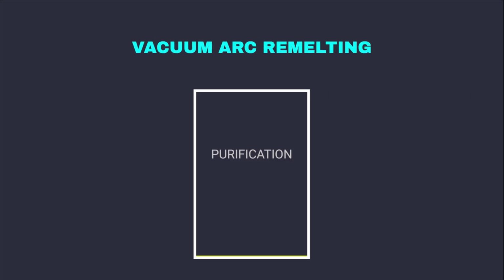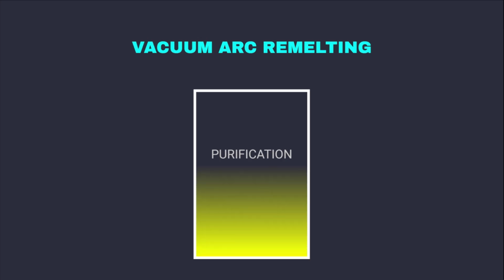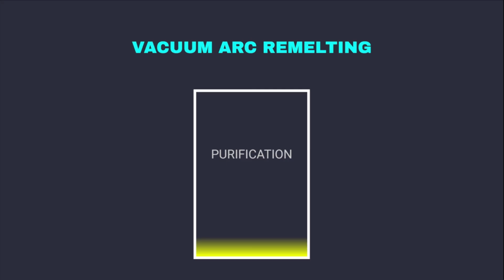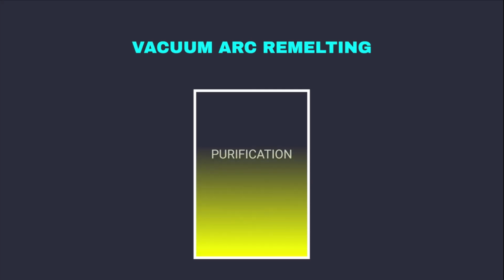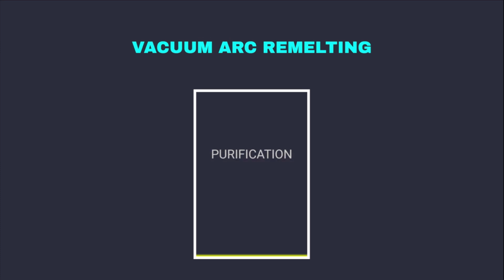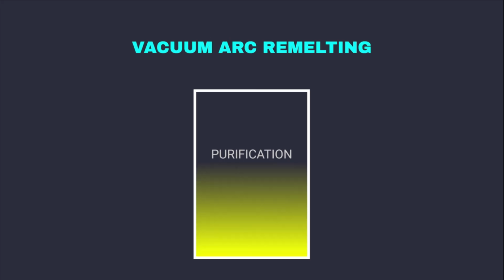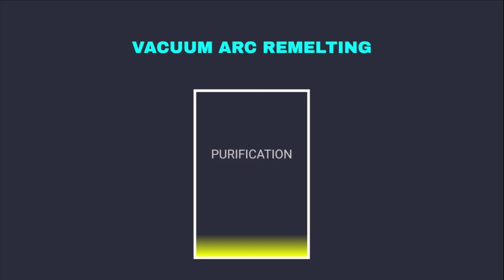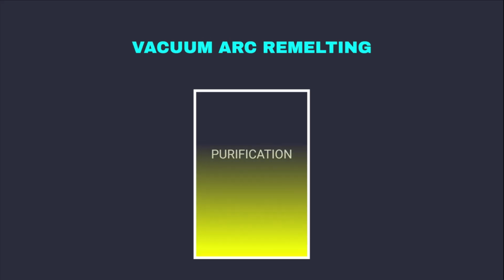Raw titanium sponge, the porous product of the Kroll reduction process, is unusable for aerospace applications until it is consolidated and purified. The acquired sponge had to undergo multiple stages of vacuum arc remelting. This process involves pressing the sponge into electrodes and melting them under high vacuum conditions, often 2 or 3 times, to remove volatile impurities like magnesium chloride and ensure chemical homogeneity. The resulting titanium ingot was then forged and rolled into the specific sheets, plates, and billets required for the Blackbird components. Maintaining purity during this conversion was paramount, as even trace contaminants could lead to catastrophic structural failure under Mach 3 stress.